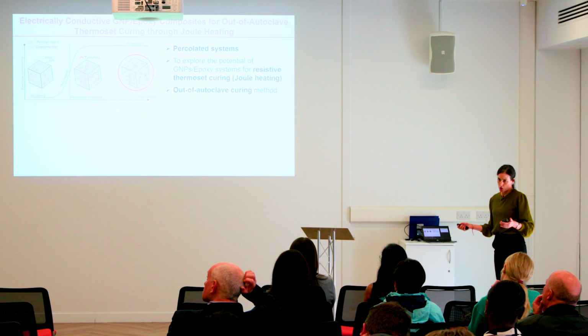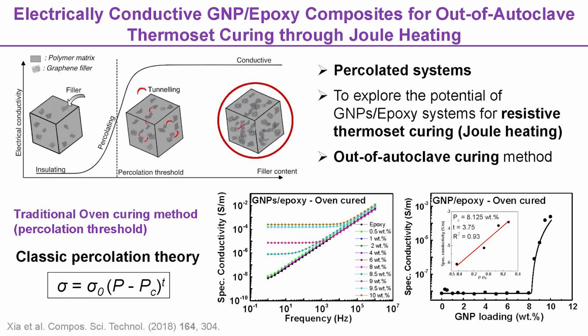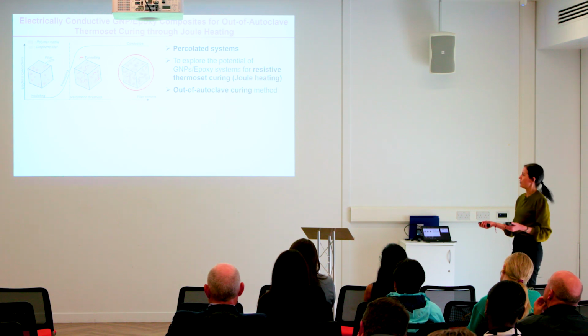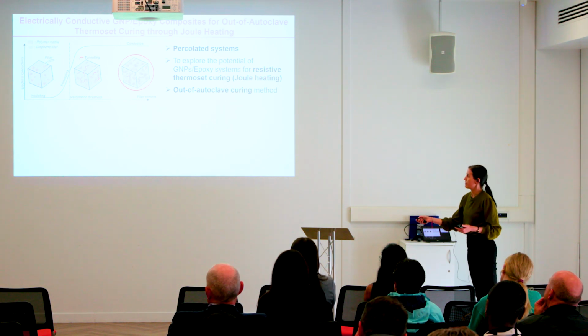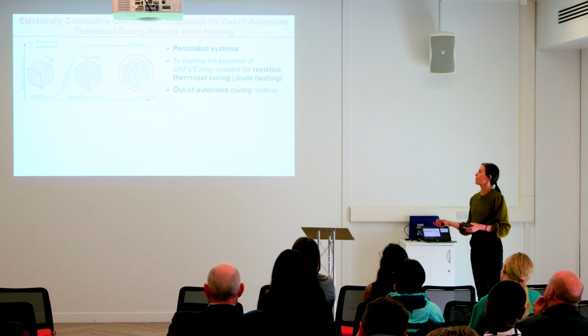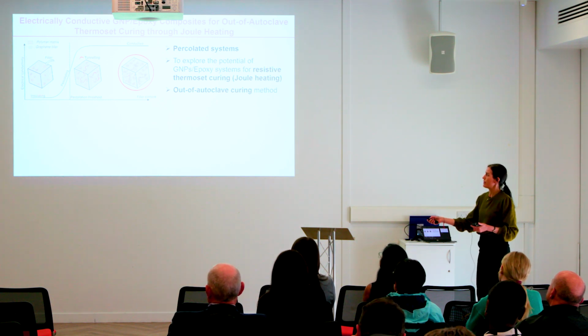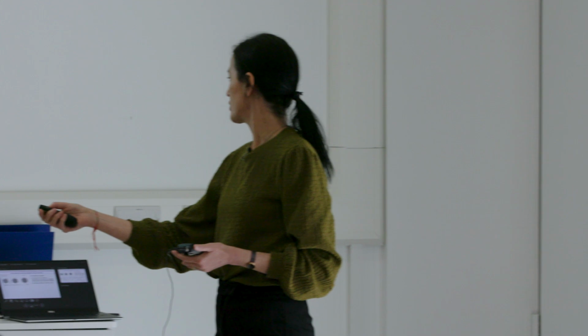So, as we probably all know, when we incorporate an electrically conductive nanofiller, for example, graphene, into a non-conductive polymer, for example, epoxy, we will see the typical behavior of a percolated system. Basically, when we are at very low loadings of filler, even though they are electrically conductive, since they are not in contact with each other, this material won't be conductive. We won't be able to measure any conductivity. We need to add more and more conductive filler in order to start creating these conductive paths.